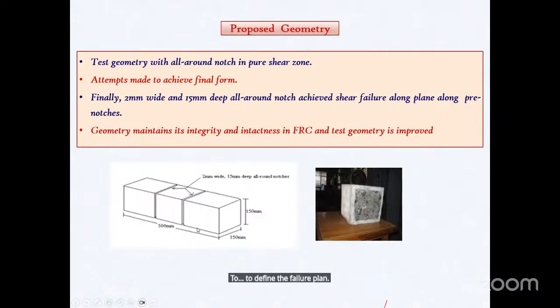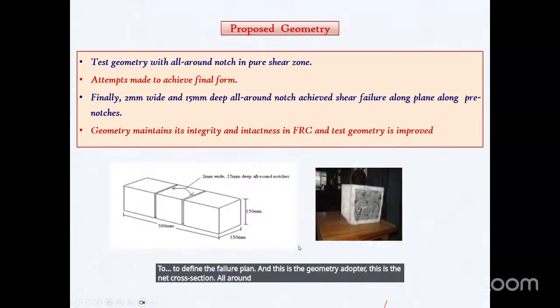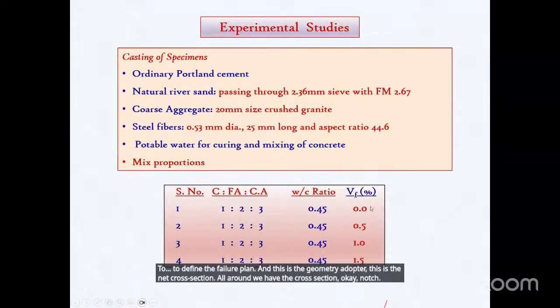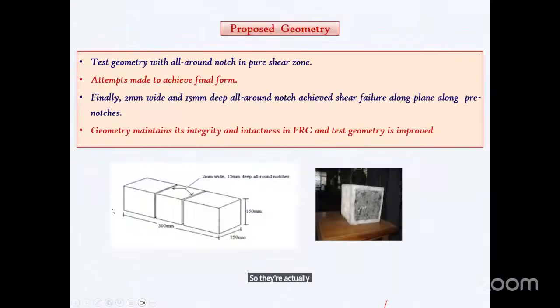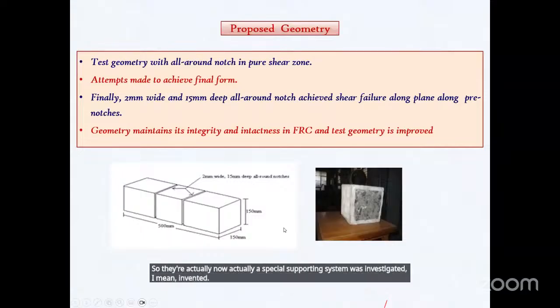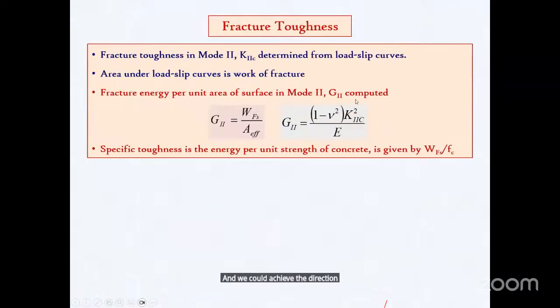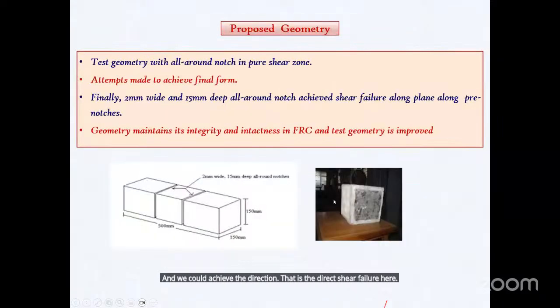And this is the geometry adopted. This is the net cross section. All around we have the cross section notch. So now a special supporting system was invented, and we could achieve the direct shear. That is the direct shear failure here. This is the direct shear failure. There is no flexure failure, there is no mixed failure. This is the special setup; a number of trials were made, and finally we could achieve this.